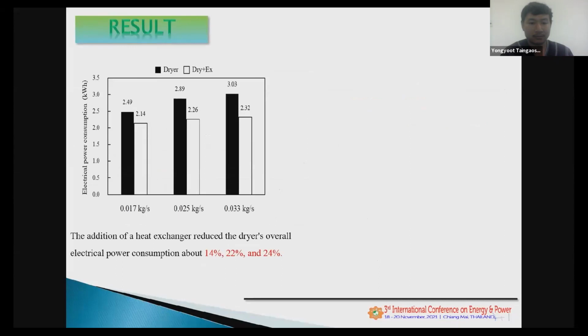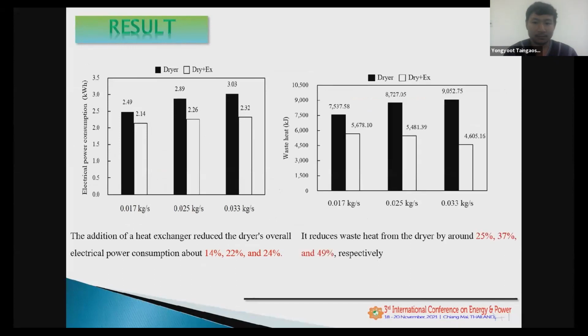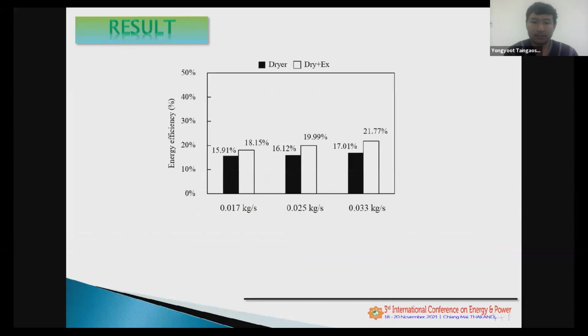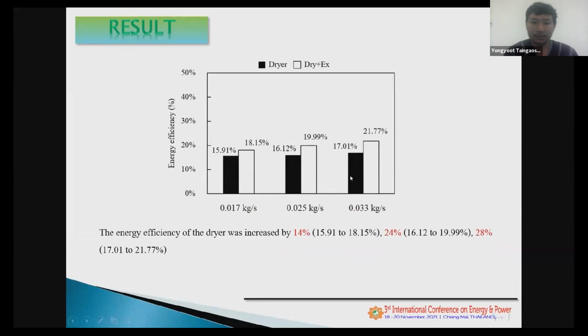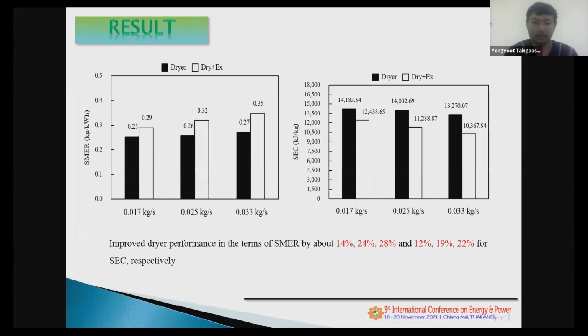The addition of a heat exchanger reduced the dryer's overall electrical power consumption by about 14%, 22%, and 24%. And it reduced waste heat from the dryer by around 25%, 37%, and 49% respectively. The energy efficiency of the dryer was increased by 14%, 24%, and 28%. In terms of SMER, by about 14, 24, and 28%, and 12%, 19%, 22% for SEC.